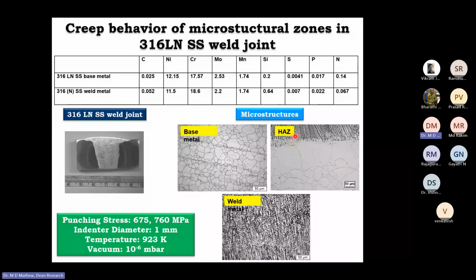And then you have the heat affected zone. That means the region immediately next to the weld metal is having a large grain size. And as you move away from the heat affected zone, the grain size decreases. So using the impression creep machine, we carried out creep tests on the base metal, heat affected zone, and the weld metal.